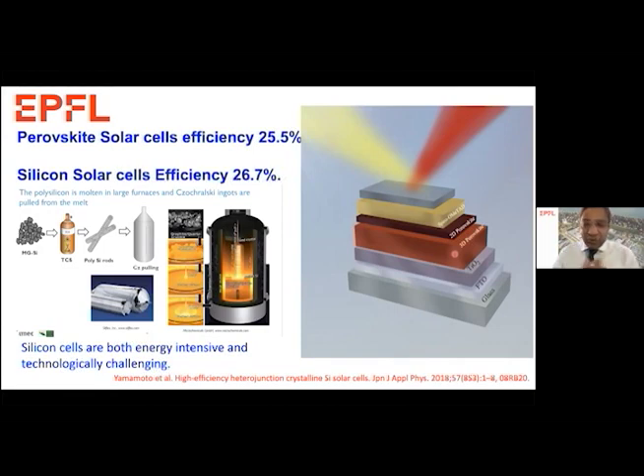But another beauty of these solar cells is that we can also inject carriers. For example, I inject positive charges through the hole transporting material and electrons from the ETL layer. Then I can get emission coming from this perovskite material. So it's a dual functional chip. In one way, it generates electricity by taking sunlight. At the same time, if we inject carriers, it gives you light.